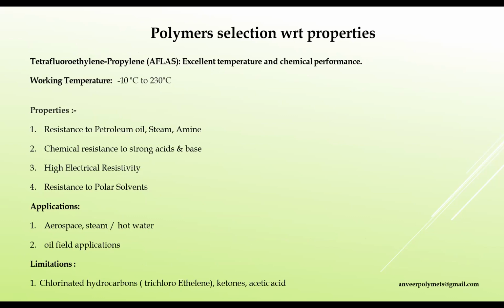Now tetrafluoroethylene propylene, that is AFLAS. It has excellent temperature and chemical performance. Working temperature is -10 to 230 degrees Celsius. It has resistance to petroleum oil, steam, amines, and chemical resistance to strong acids and bases. It has high electrical resistivity and resistance to polar solvents. It also has ozone resistance, and resistance to radiation to some extent. Applications are in aerospace, steam, hot water up to 204 degrees Celsius, and oil-field applications. Limitations of AFLAS: it is not recommended for chlorinated hydrocarbons, that is trichloroethylene, ketones, and acetic acid environments.